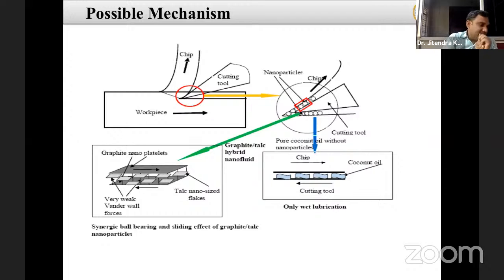So what is the possible mechanism for why this happened? Why are the forces lower and why does the surface roughness improve? This is the possible mechanism which I propose. When we throw that mist lubricant at the tool chip interface at very high speed and high pressure through the nozzle, those nanoparticles come into the contact between the tool and chip interface. Because of that, they slide over each other, the tool chip interface is not in direct contact, and they make a very thin tribofilm at the interface between tool and chip. Because of that, the forces acting on the tool chip interface are less. So the resultant force is less, and it also improves the surface finish.